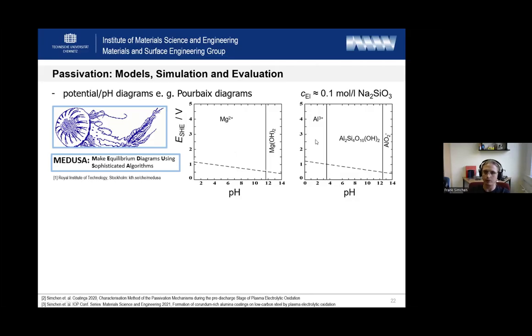And there you can say, okay, most electrolytes which are used for the PEO of aluminum, they are alkaline silicate solutions. And we see here, if we apply some silicate, sodium silicate to our electrolyte, we see that the stability regions of aluminum are extended in alkaline direction. So, of course, these diagrams just consider thermodynamic applications and don't respect any kinetic limitations. And what is more challenging, they finished at 5 volt, and in PEO we go up to 500 volt.